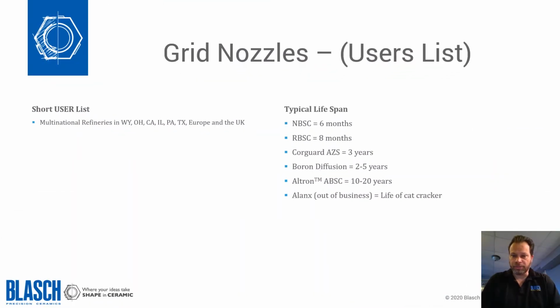Here is a short user list of people that have implemented the ceramic Altron grid nozzles. Over the years, there have been many materials that have been tested to replace the metallic nozzles, from nitride bonded silicon carbide to reaction bonded. Altron seems to be falling in the 10 to 20 year lifespan. We haven't really seen much abrasion of the ceramic itself. Often it's the metallic holder or collar that's around the nozzle where we see the abrasion.